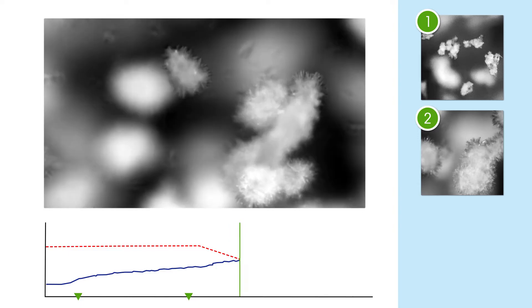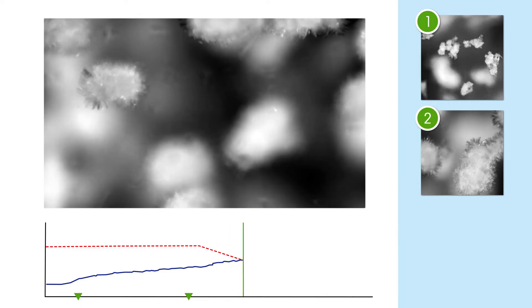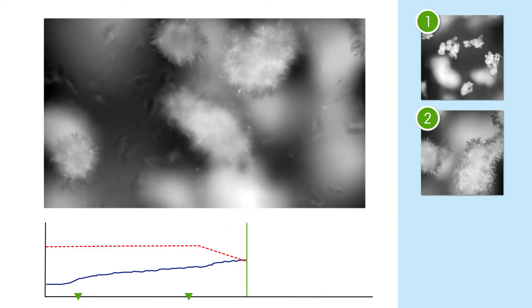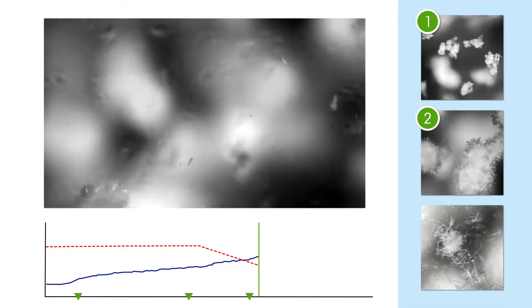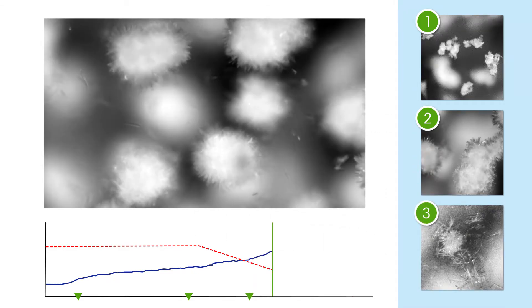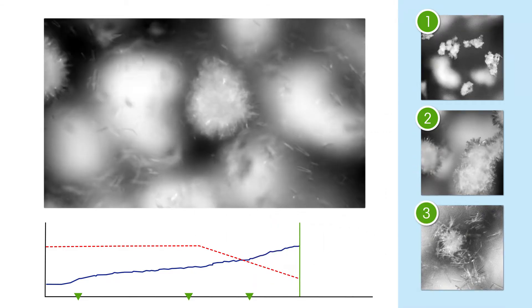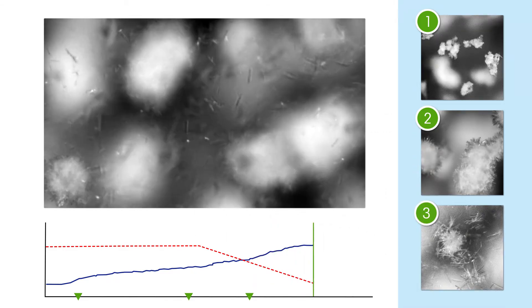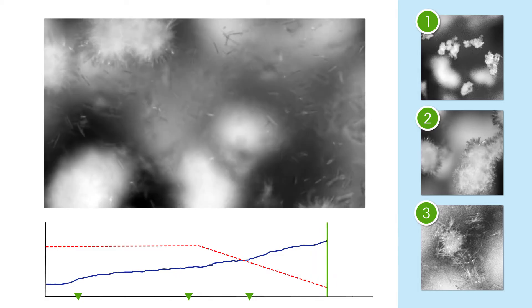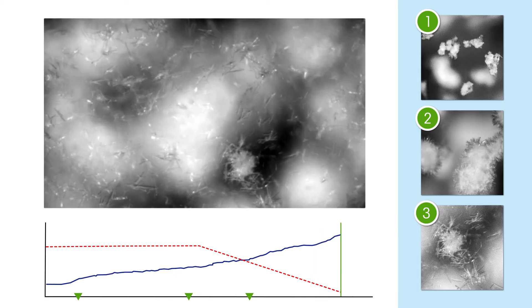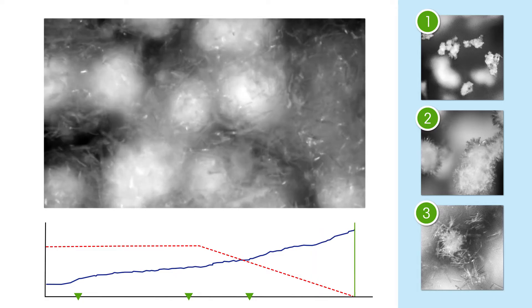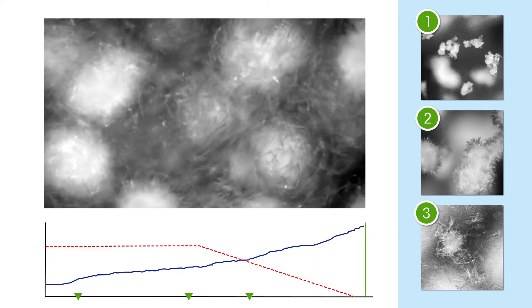The final mechanism observed makes it very clear why the filtration rate is slow. The delicate needles broke away, resulting in a significant secondary nucleation event, which was accelerated by a fast cooling rate towards the end of the process.